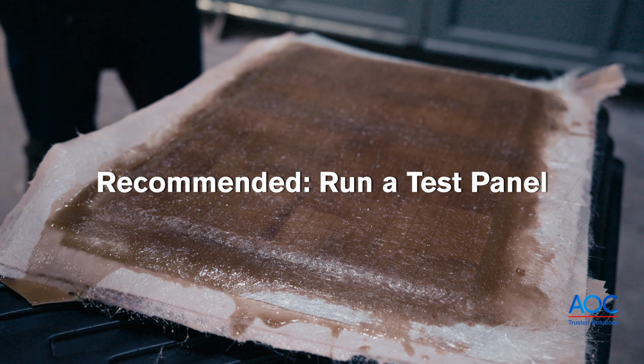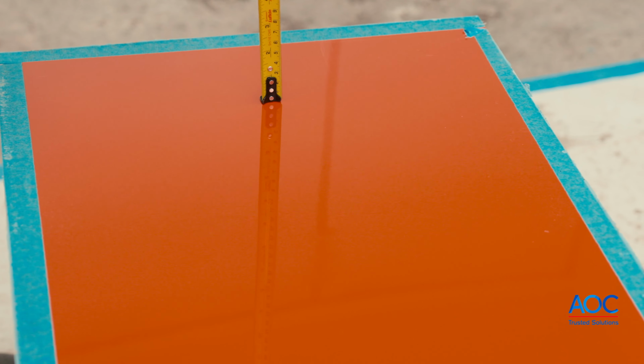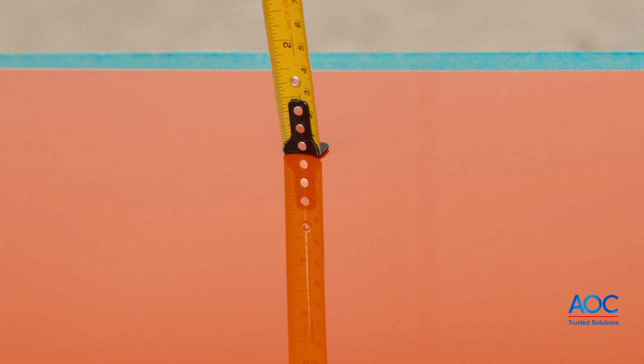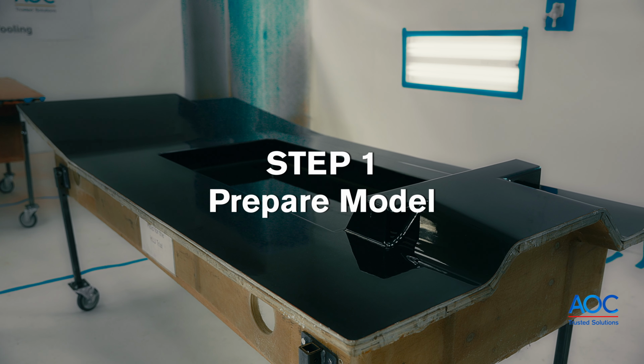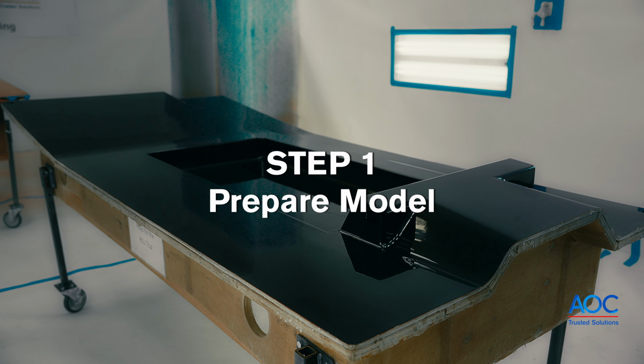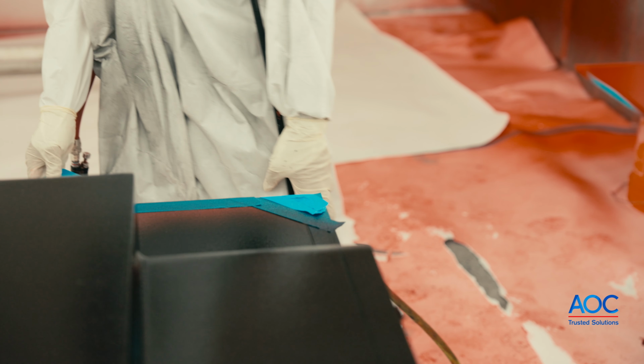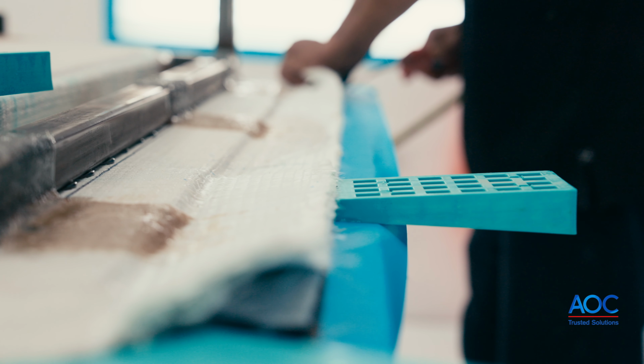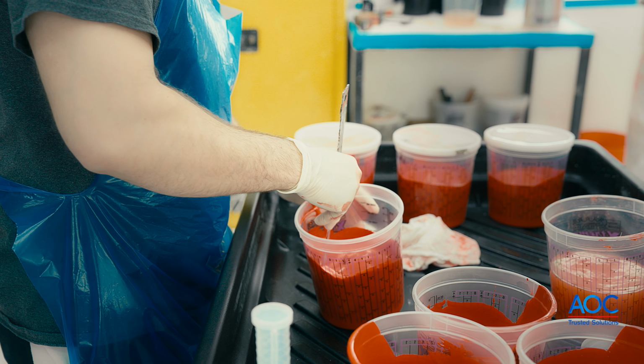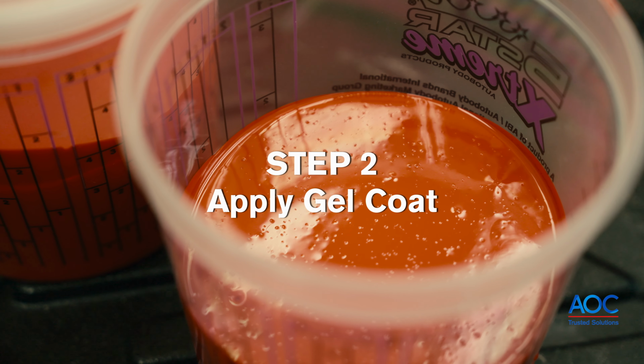Before starting work on the tool, we recommend creating a test panel. This will lay the groundwork for optimal glass ply, resin wet out, and surface finish quality. Start preparing your master model by applying a complete mold release system to ensure the mold releases from the master cleanly after curing. The next step in the process is to apply the gel coat to the master model.